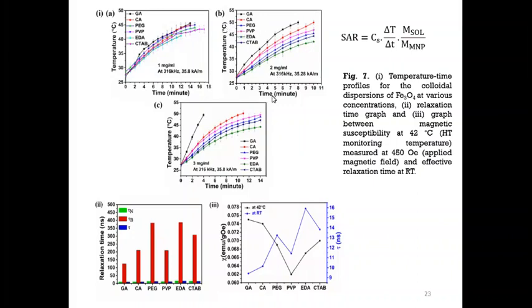But if suitable magnetic parameters are there, the heat can be generated in less than 5 minutes too. So in around 5 minutes, the temperature is around 45 degrees. So based on the type of coating, even if it looks spherical, there is a difference in the size and in the magnetic anisotropy, and hence the relaxations are also different.